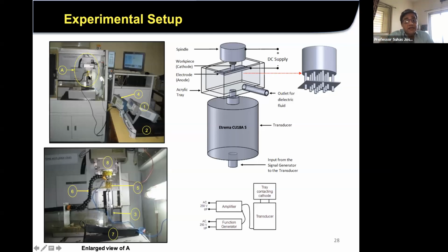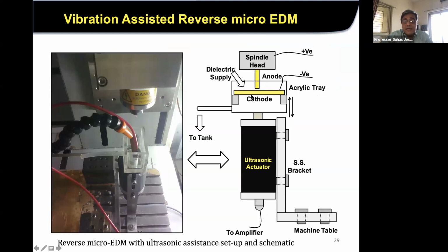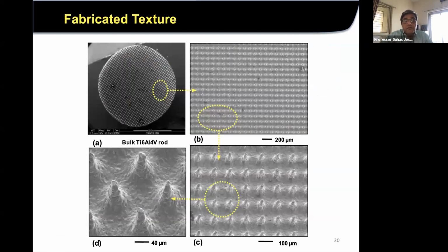This is another experimental setup, work done by my PhD student, where rods of very large sizes can be made. You can see here is an ultrasonic actuator, but actually these frequencies are lower. With the help of this actuator, we could make a variety of structures. For example, this is an 8 millimeter diameter titanium rod, and you can see these kinds of structures formed from here to here. Of course, these are orderly structures, but the process has a lot of capabilities. We have later explored it for uneven surfaces and very flexible electrodes, and as long as they don't contact the surfaces and short circuit, this process can work.